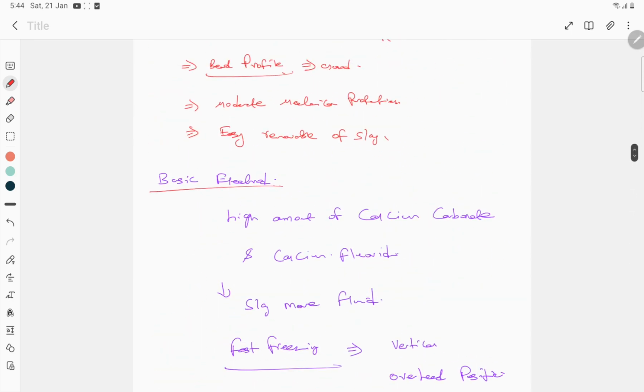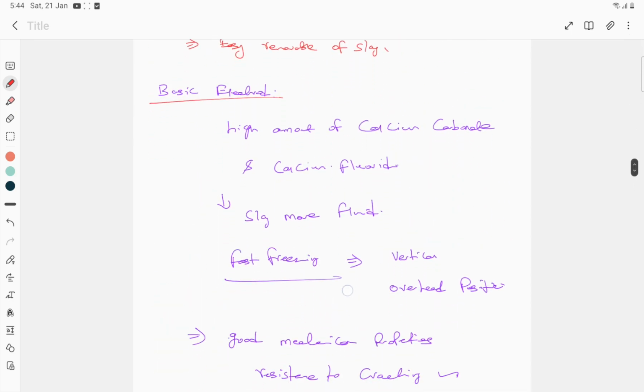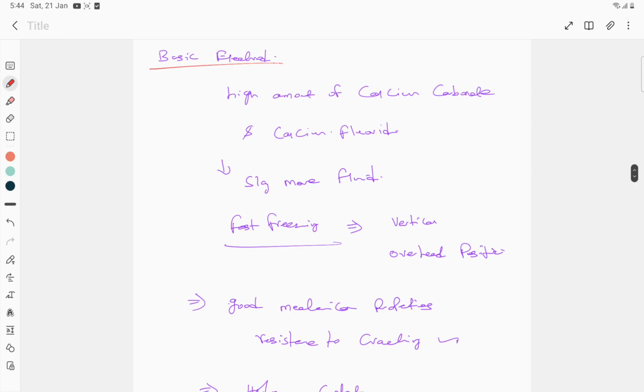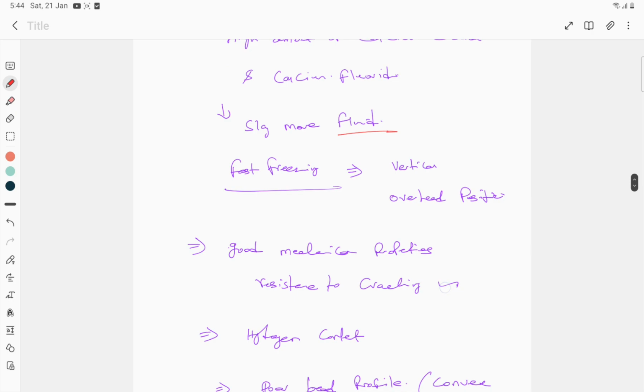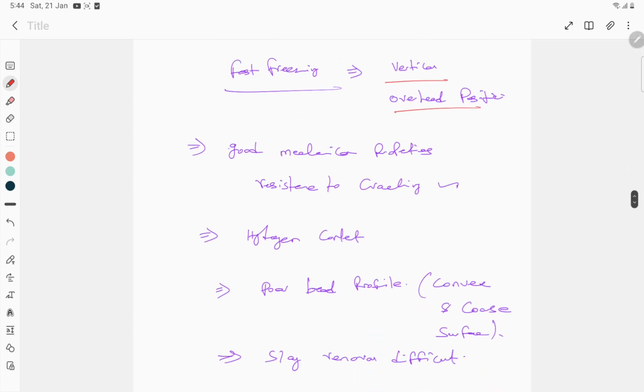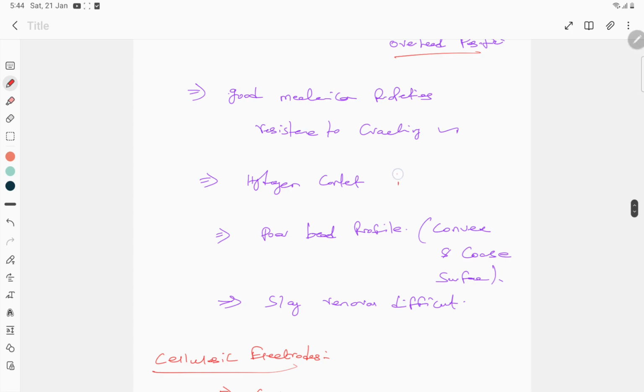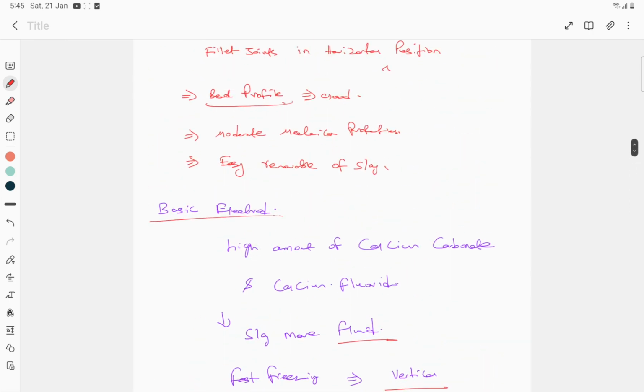Whereas in case of a basic electrode, it contains a high amount of calcium carbonate and calcium fluoride. It will help us to make the slag more fluid, and the freezing is also very fast. And as the freezing is fast, it is possible to use the electrode in vertical and overhead welding positions. We can get very good mechanical properties using this electrode. Okay, the hydrogen content is also less. But the bead profile will be comparatively poorer than what we have seen in the rutile based, and slag removal will be difficult in this basic electrode.